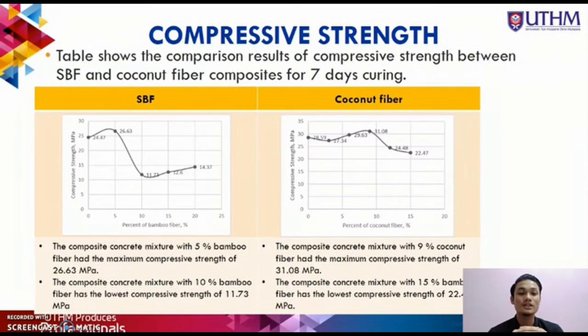For the compressive strength result, if the percentage of fiber content is increased, it reaches its optimum value, which makes the mixing procedure more compatible and workable. In this comparison, the optimum percentage of SBF is 5% while for coconut fiber it is 9%. So, the compressive strength value will decrease when the percentage of fiber exceeds the optimum value.